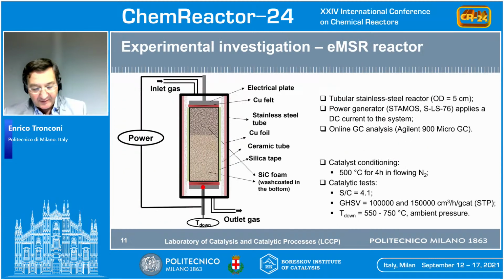So we placed the silicon carbide foam wash coated with the rhodium on alumina catalyst inside our tubular stainless steel reactor. So the feed gas was preheated in the uncoated upper part of the foam, and the methane steam reforming reaction proceeded in the downstream wash coated portion of the catalyst sample. We ran blank experiments initially over an empty silicon carbide foam to rule out any methane conversion up to 750 degrees C.